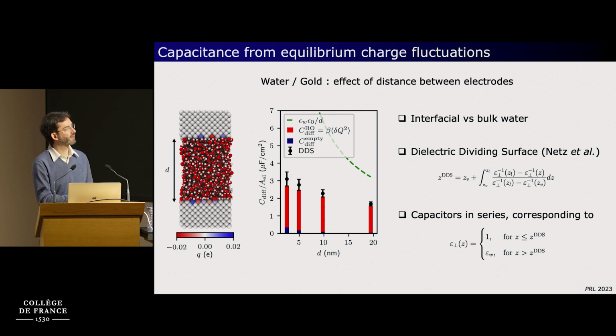And this corresponds to capacitors in series. So you have vacuum between the first electrode atom plane and this dielectric dividing surface, and then you have bulk water and then another DDS on the other side. And this allows you to define an effective width of the liquid slab. And if you now use the same prediction but with distance correctly defined, then you get to this black prediction, which is in much better agreement with the simulation results.